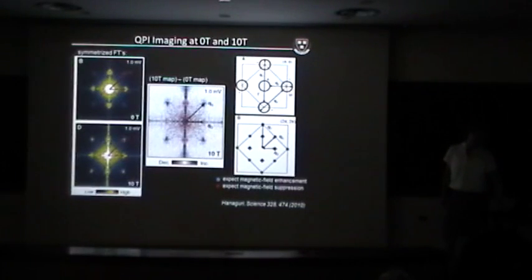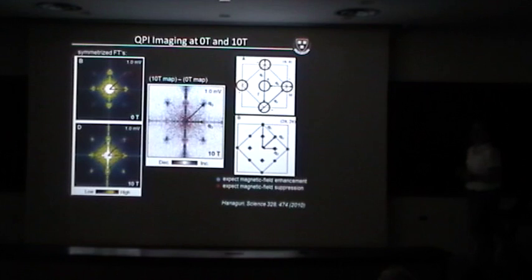I know another objection that was raised actually in your paper to the second Hanaguri experiment was that there's only 3 wave vectors that we care about here, and one of them corresponds to a Bragg vector, so there was some confusion about whether this would be meaningful because of the Bragg vector and the QPI vector mixed up together. And I think the argument that I would make is that the Bragg vector is much sharper. It can be collapsed, as you know, onto a single pixel, and so I don't think that can explain the entire broad change in that.